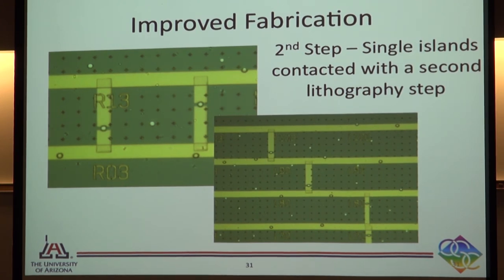My island is 2.3 micron, and it will have a bigger coherence length in my indium arsenide, my semiconductor, which is supposed to start behaving like a superconductor. I was just talking about aluminum, where it's 1.2 micron when it's good, and it's usually 100 nanometer when it's real material. What I know is that I will have the cleanest possible indium on top of the cleanest possible indium arsenide, because it's all done in one MBE chamber. So it will be very interesting to first measure the coherence length before we start doing any optics experiment.